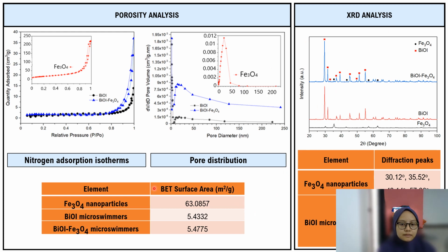The BET surface area also supported this finding, since the magnetic nanoparticles have a very high surface area, and the surface area of the bismuth magnetic microswimmers is slightly increased compared to the bismuth microswimmers.